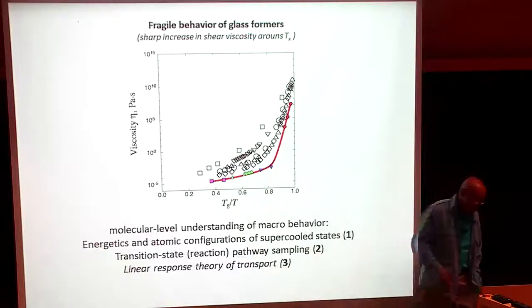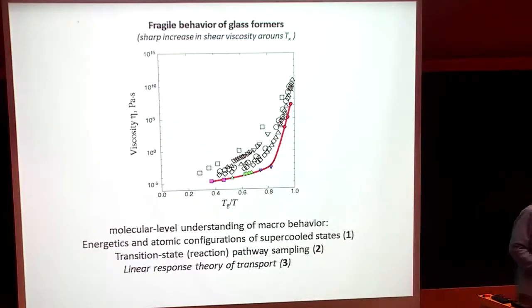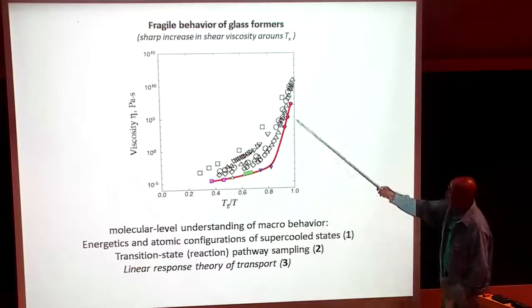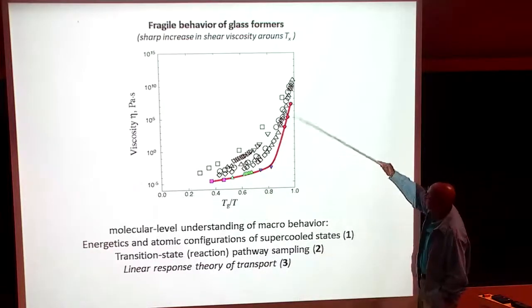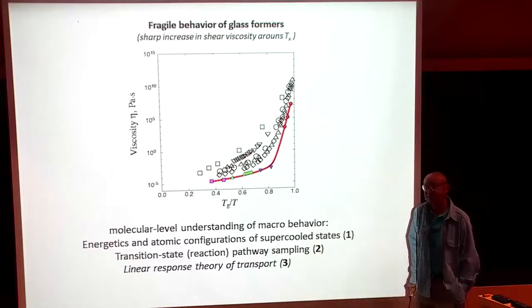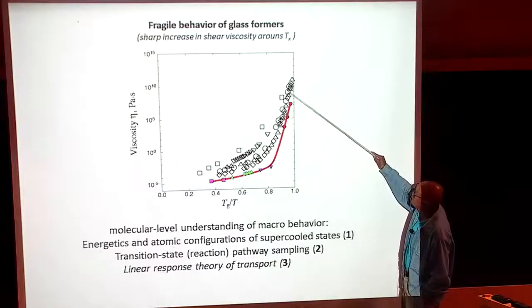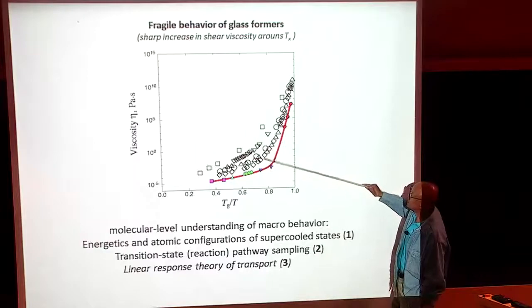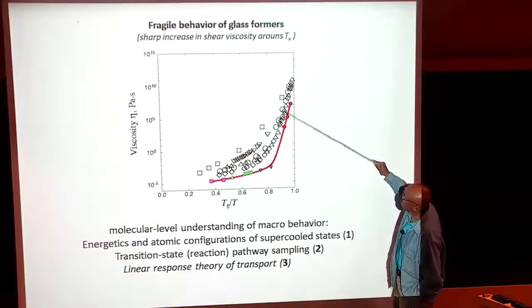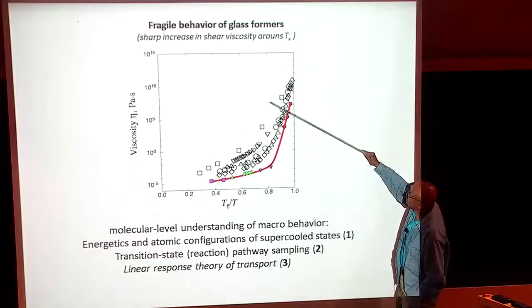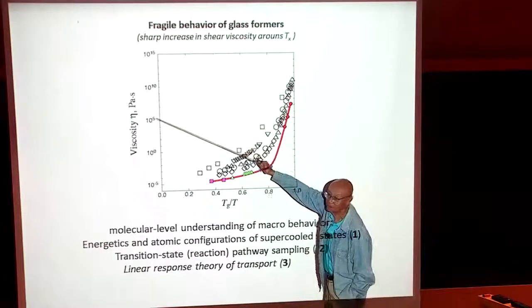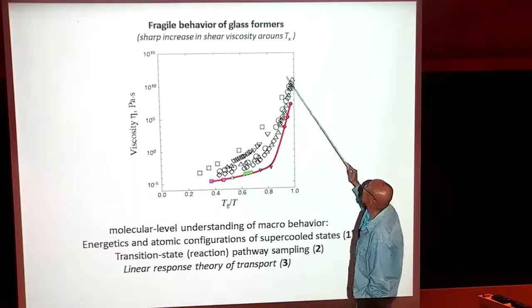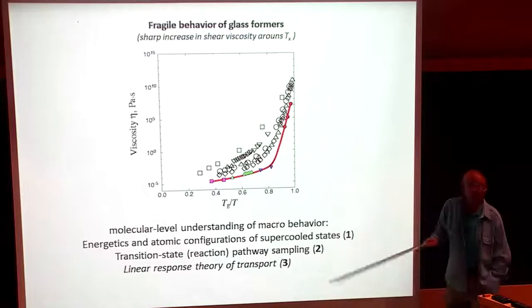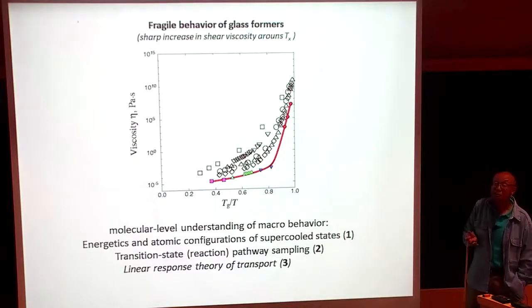Tg is actually a convenient property to normalize. It's like a scaling parameter, if you like. So Tg, in this particular context, is that temperature at which the liquid has a viscosity of 10 to the 13 poise. So if I have a liquid with a viscosity curve like that, viscosity as a function of temperature, as I go to lower temperature the viscosity goes up, and at the temperature where the viscosity has that magic value of 10 to the 13 poise, or 10 to the 12 pascal seconds, there's a factor of 10 between poise and pascal seconds, I call that particular temperature Tg for that liquid. So each system has its own Tg.